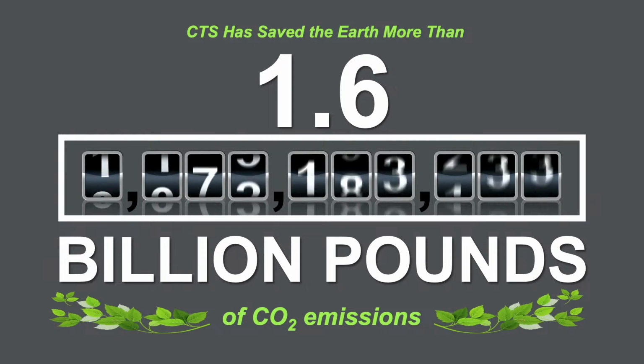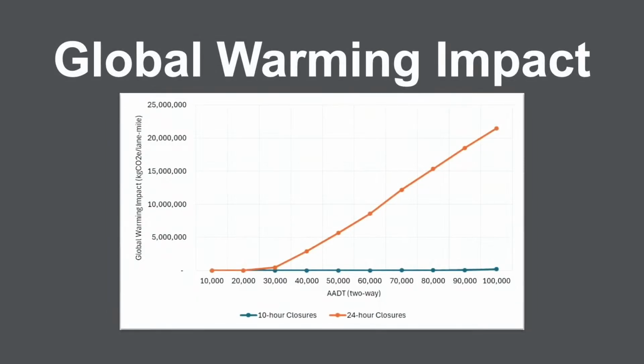Now, everybody knows that the global warming impact of Portland cement is significant. But did you know that the FHWA, in conjunction with the University of California Pavement Research Center, recently published their study where they looked at 24-hour closures versus 10-hour nighttime closures. And what they found is that the 24-hour closure had a much higher GWI, which is a global warming impact, because of all the carbon emissions from the vehicles idling in traffic. In fact, they found that the GWI based on the traffic can be up to 100 times greater per lane mile than the cement used in that same lane mile.